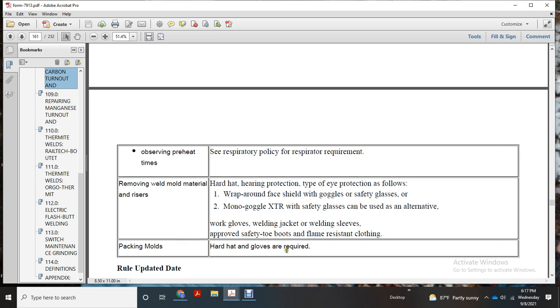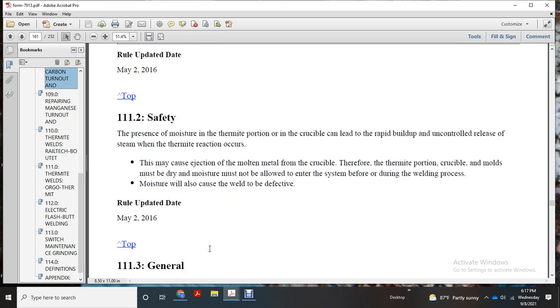Packing molds, hard hat, and gloves are required. Safety: the presence of moisture in the thermite portion or crucible can lead to rapid buildup and uncontrolled release of steam. The thermite reaction can occur with the ejection of molten metal from the crucible. Therefore, thermite portion, crucible and molds must be dry. Moisture must not be allowed to enter the system before or during the welding process. Moisture will also cause the weld to be defective.